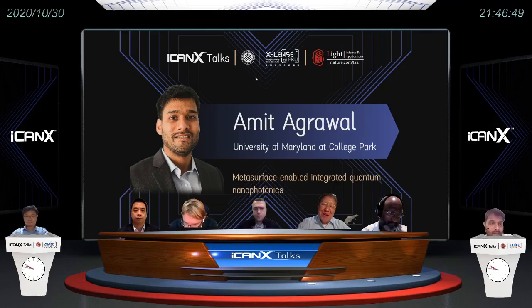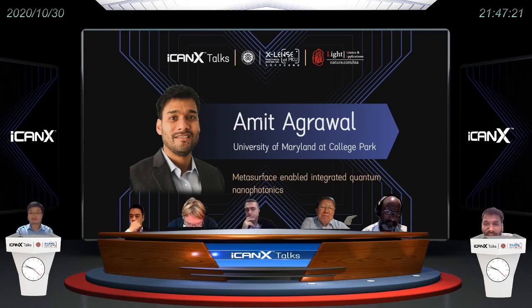Yeah. Okay, so we use electron beam lithography. With electron beam lithography, we are basically limited by the write time. So the largest, let's say, we are making for this program is a chip that is shown here. This blue dot is approximately a centimeter size. There are 3 one centimeter size metasurfaces and 3 smaller metasurfaces. Writing these metasurfaces will take approximately, I would say, a whole weekend. But there are faster e-beam write machines that are 100 megahertz, and you can probably cut that time down to 24 hours. But it is a serial process.